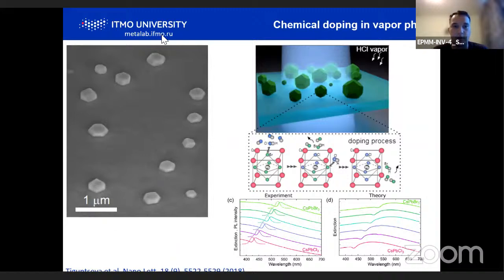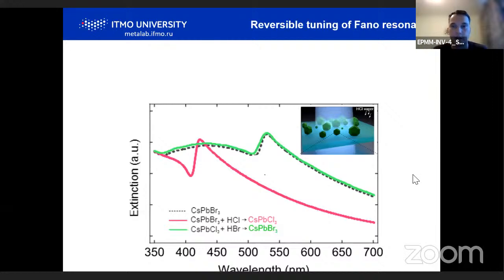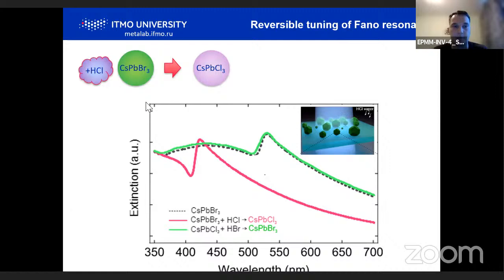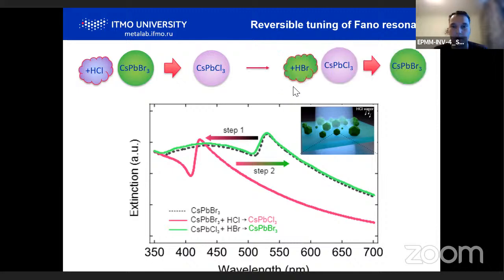And the same story can be applied for an array of nanoparticles made of halide perovskites. And you see here some experimental results, how we tune this Fano dip resonance over half of our visible range, which is confirmed by our theoretical calculations. And it's interesting whether it is reversible or not. Of course, yes. If we take the nanoparticles made of bromide perovskites and put them in HCl acid and wait for some time, we can shift our extinction spectra over more than 100 nanometers to the UV range. And then we can put exactly the same nanoparticles in HBr acid, and then we get the same nanoparticle as we had in the very beginning.